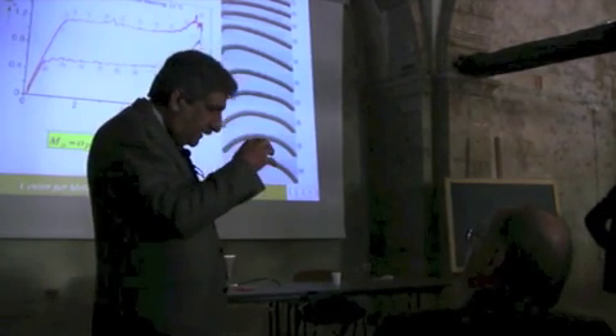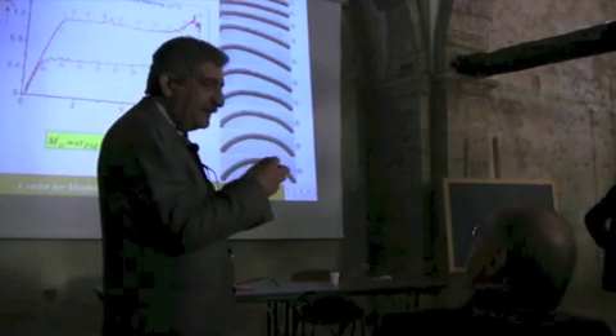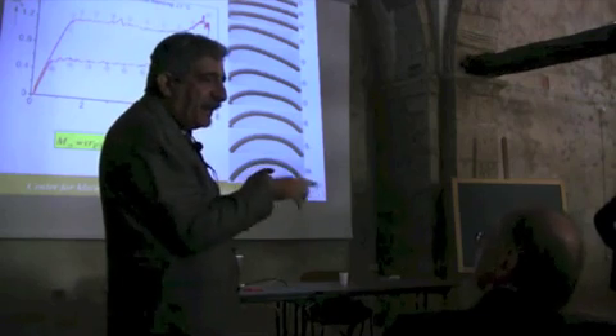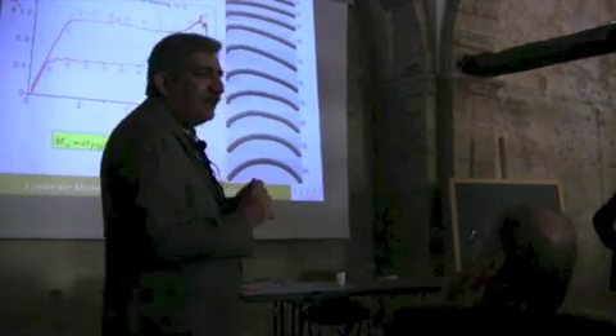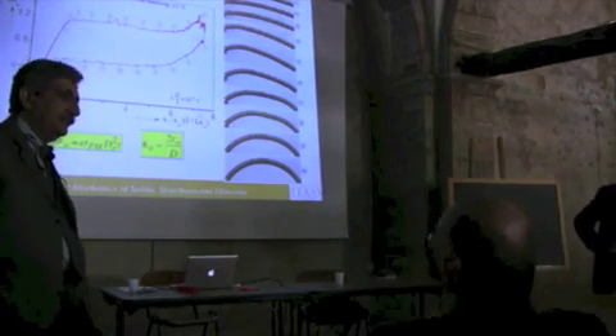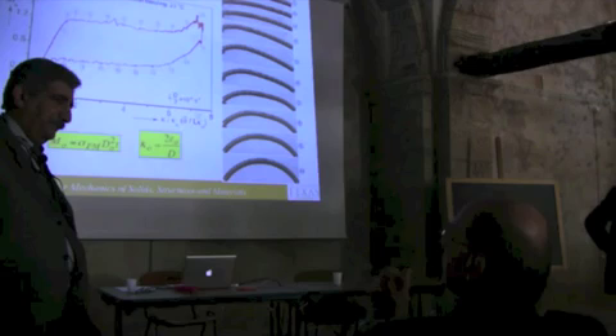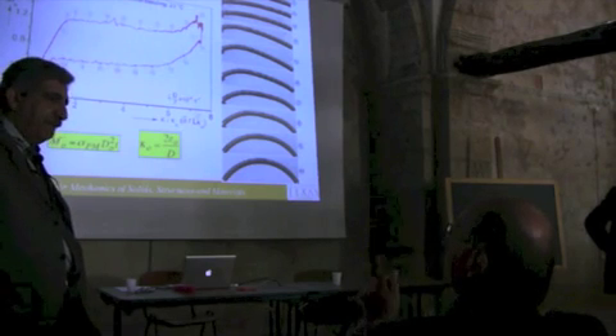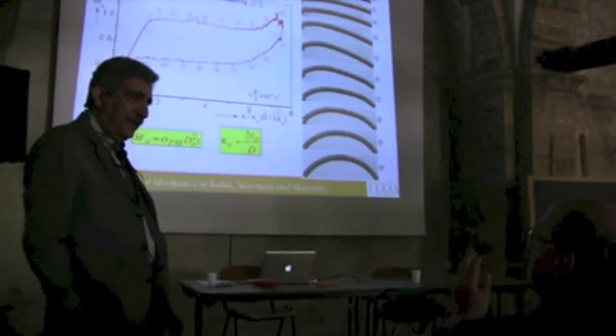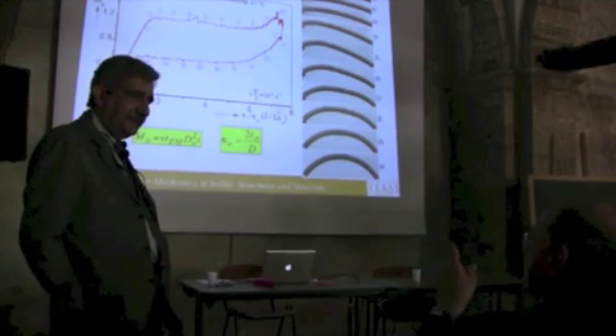But that bifurcation, for the early one, it basically leads to some asymmetry in the bulge. Instead of being axisymmetric, it may be a little bit non-axisymmetric. And if you inflate it a little bit more, it recovers. It's a temporary disturbance. You understand? Yes. Because in my case, the bifurcation is afterwards. Okay. Because in a paper by M&MoCS, it was shown that in particular cases where non-linearities in material behavior are involved, you have to have bifurcation after. No? I think that this is a good point to continue modeling of some phenomena as the one of the balloon show. Yes, we are in agreement. Perfect, yes.